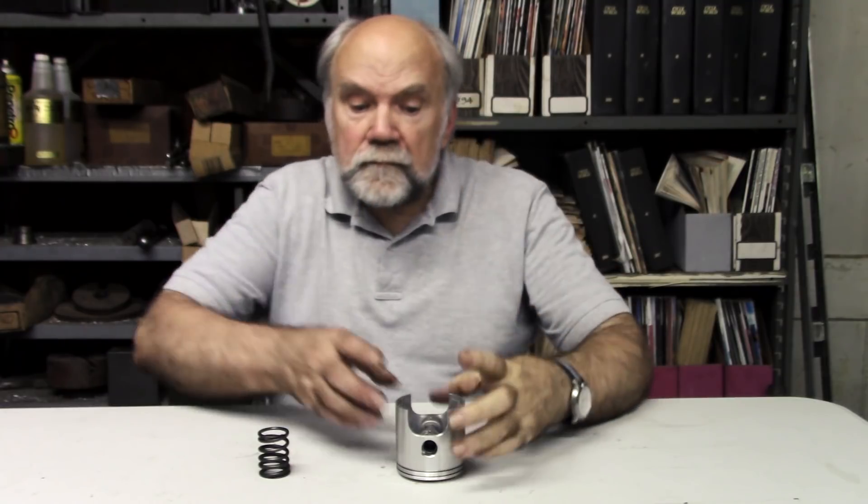Yamaha did a thermal study; they developed a thermal model which predicted the temperatures of all parts of the piston, including the crucially stressed area around the wrist pin boss, because fatigue failure is accelerated by high temperature. Yamaha, and presumably the other teams, studied temperature distribution in their pistons and found ways to reduce the temperature in the crucially stressed areas, and they were able to make five engines last through 18 races.